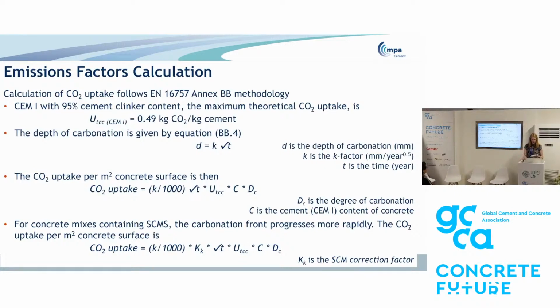We also multiply by the degree of carbonation. So this is a measure of how fully the concrete has carbonated within the carbonation front. Now we know we don't get a full conversion of calcium silicates and oxides to calcium carbonate, so that degree of carbonation gives the proportion of the material that is carbonated. The EN 16757 standard actually sets out a range of factors for that degree of carbonation for different concrete strengths and different exposure conditions. So combining all of that together along with the quantity of the CEM I in your concrete, you can work out the emission factor.